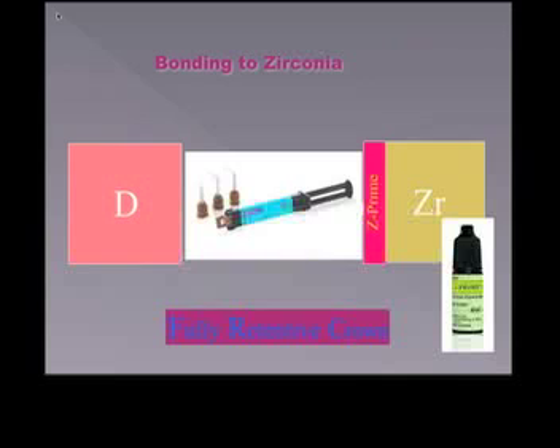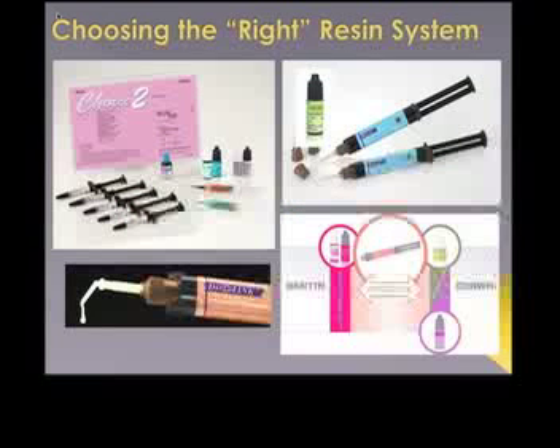So light cure cements are advantageous in thin veneer preparations because of the color stability. The dual cure resins, though, offer the clinician confidence of cure in hard-to-reach areas and under opaque, light-reflecting restorations. So the self-adhesive cements are dual cure, containing acidic adhesive monomers.